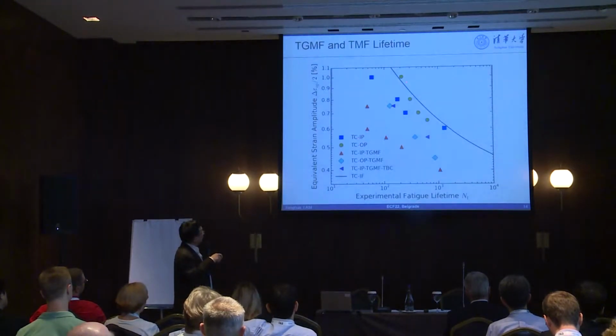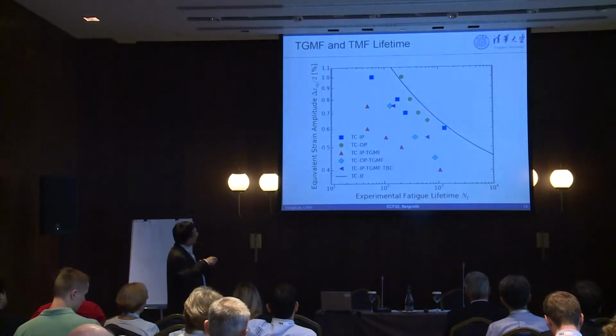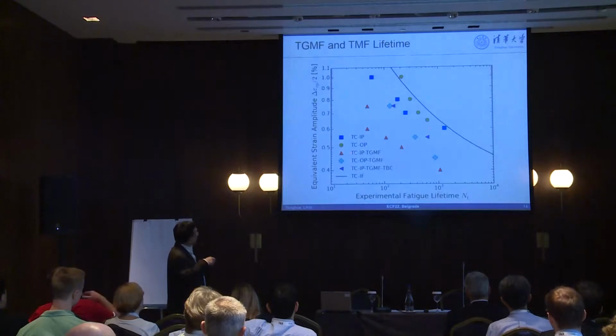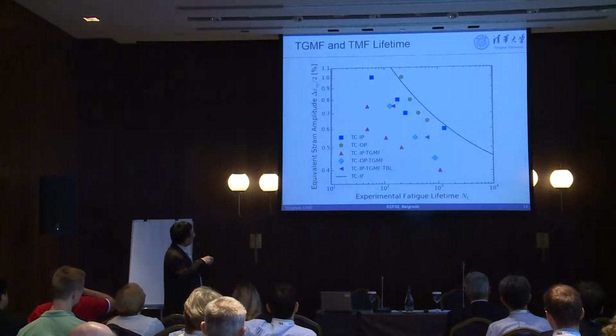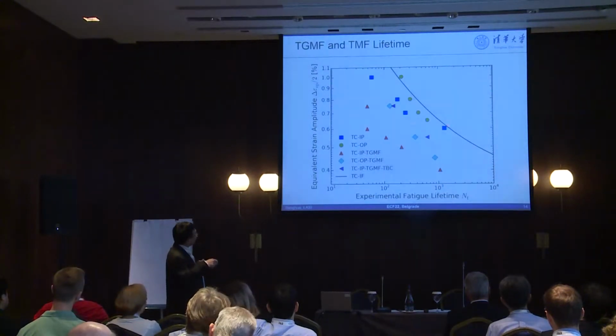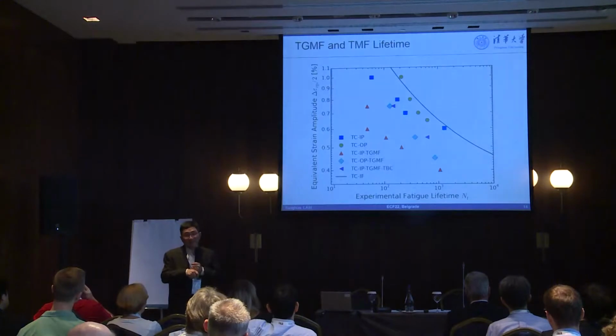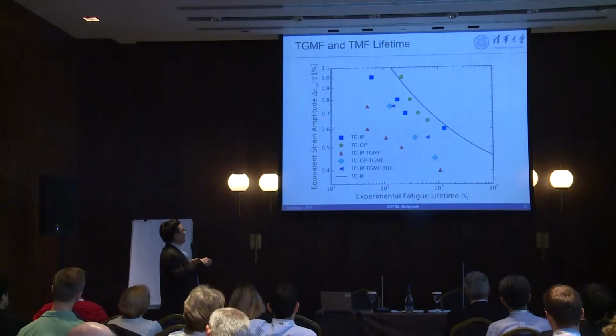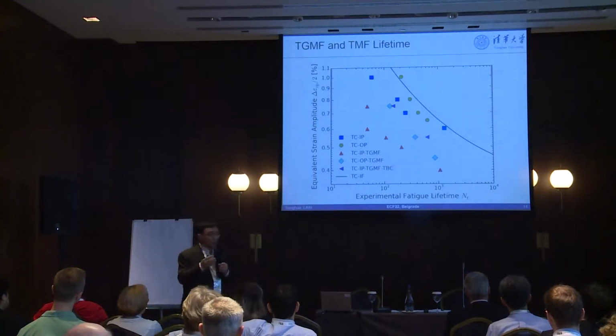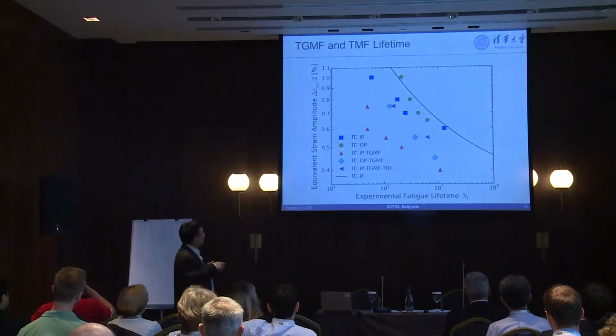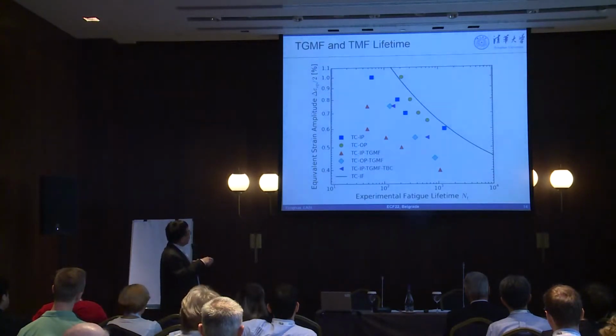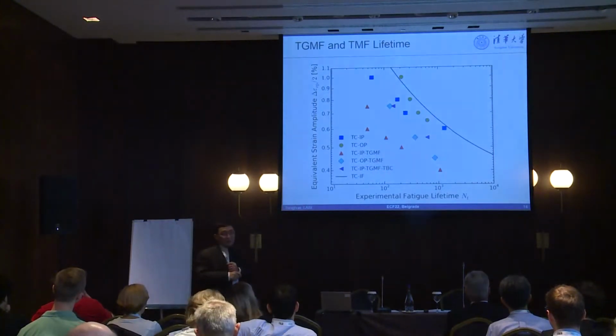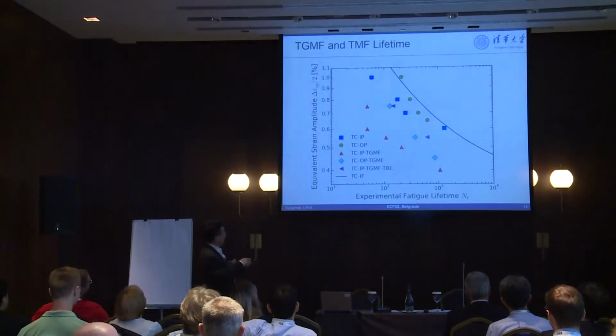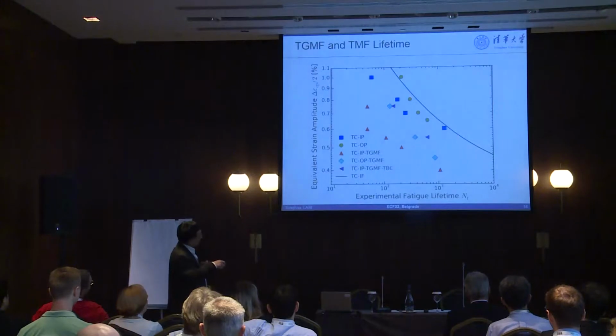And that means what you see here is the in-phase case. This line is the isothermal. And that is out of phase. The red line is the TGMF, in-phase TGMF here. And you see the difference between them, almost 2 decades, right? And okay, you see the life cannot be so long. Therefore, the reason is that we can perform the TGMF test only at very low speed. And okay, that is the TGMF out of phase, and that is the one with the so-called TBC, the thermal barrier coating introduced on the specimen. Therefore, of course, life becomes better. But you see that the difference to the other is still significant.